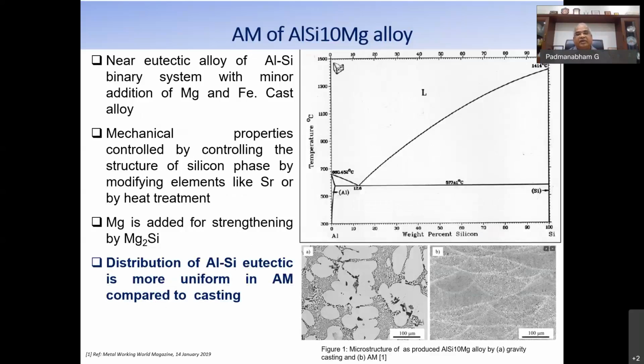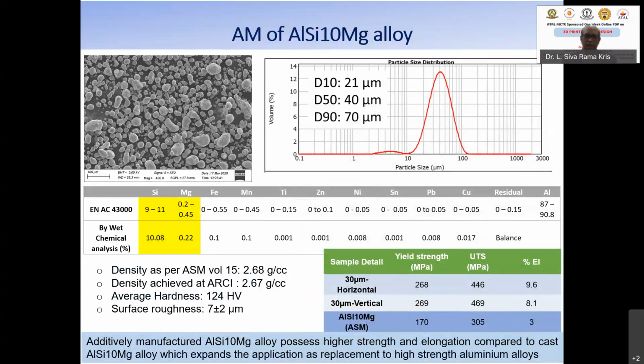And you can see in the microstructure that the aluminum silicon eutectic is nicely, uniformly distributed in the additive manufactured part rather than the cast part. The left one is the cast and the right one is the AM one. You can see the fine distribution. And then we have done a lot of experimentation on AM of this alloy, and you can see the properties. I'll just concentrate on that part.